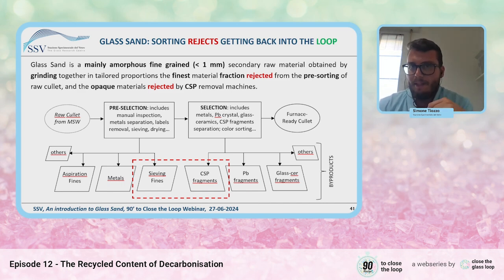What is glass sand? How do you make it? What are the regions that we are talking about? Glass sand is an amorphous fine-grained secondary raw material. Basically, it's made up of fines that are normally sieved out from the glass cullet during the cullet treatment process. They are problematic from the technological point of view, from the detection point of view, because the machines that treat cullet and remove contaminants cannot work below a certain dimension of the fragments. So the fines are sieved out because they cannot be treated and detected very well.